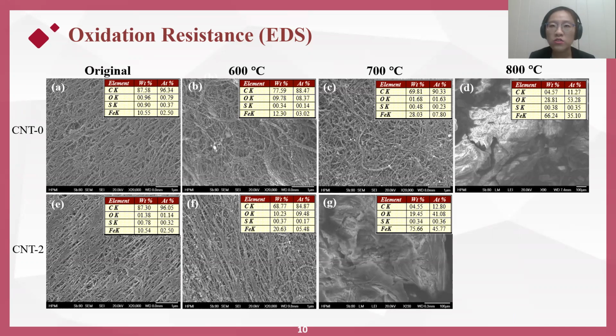This discrepancy was further magnified at 700 Celsius, when the CNT2 group completed the oxidation. The oxidation of the CNT0 group was not complete until 800 Celsius. The earlier oxidation of the water-assisted CNT2 group samples could be attributed to their smaller diameters, resulting from the removal of the amorphous carbon layer on the catalyst nanoparticles before the CNT growth.